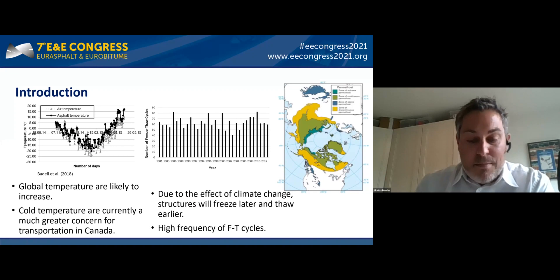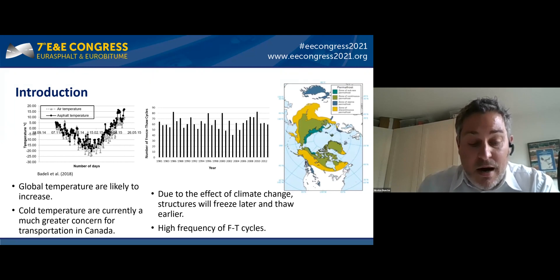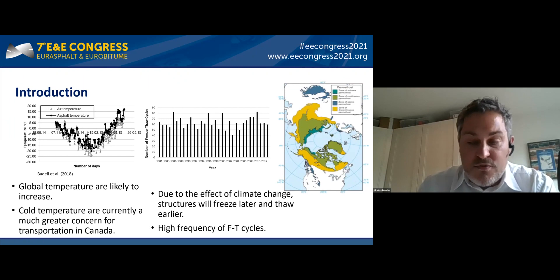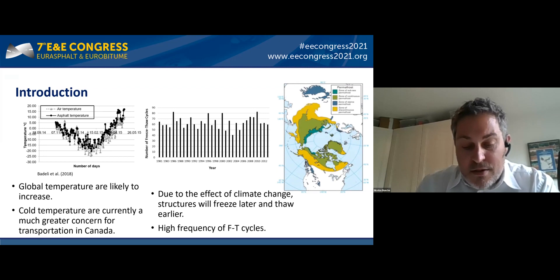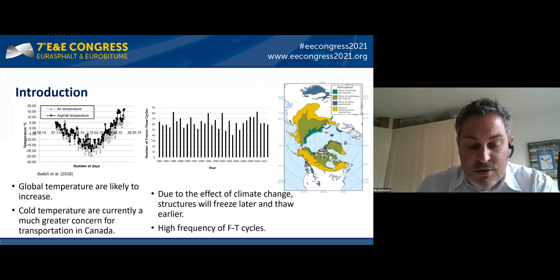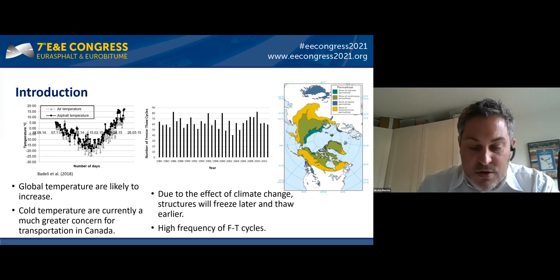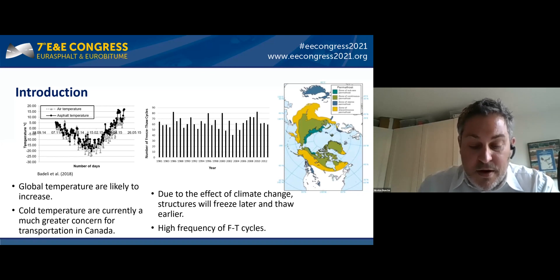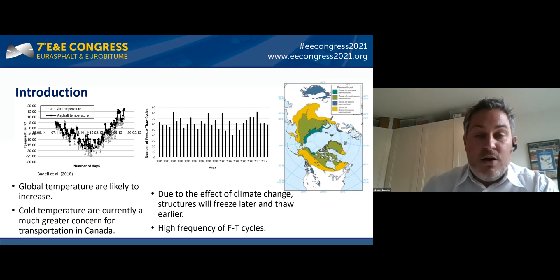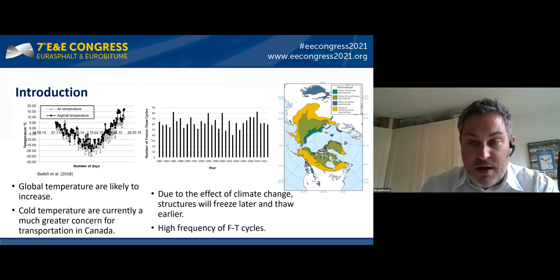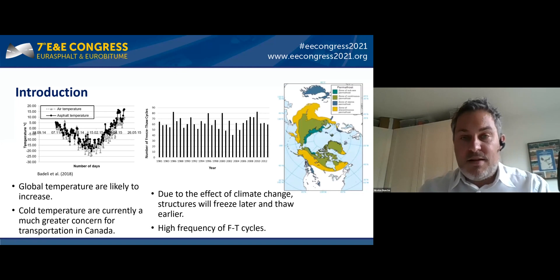On the left-hand side you can see data collected by the Ministry of Transport of Quebec illustrating daily asphalt temperature history — asphalt temperatures are higher than air temperature though they follow the same trend. According to the database gathered in long-term pavement performance studies in cold regions, asphalt pavement undergoes a higher number of daily freeze-thaw cycles. These severe temperature variations, which seasonally may reach 60 degrees, result in premature failure in terms of low-temperature or thermal fatigue cracking.